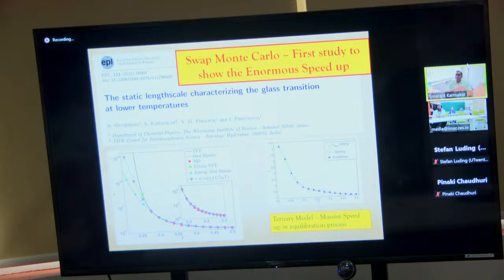Still the rates are around 10 to the minus 3, or minus 2 to minus 3, but that itself was large enough to accelerate the dynamics very, very significantly. And we could reach, or equilibrate the sample at a temperature where the estimated relaxation time can be as large as 10 to the 10 to 12. So this is nearly impossible using any conventional methods.